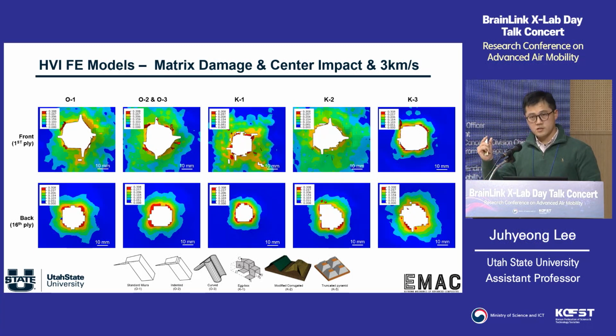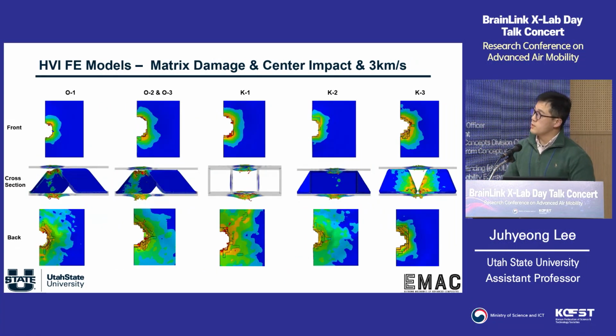So by simply changing the periodic patterns of the unit cell, you have a huge variation in the impact, right? So by studying the optimal shape design and also choosing a different material selection, you may block all the external impact compactly. Yeah. So this one is matrix damage volume-wise. You can see the impact side damage and then through-thickness damage as well as the back side. Again, you can see the huge variation in terms of the damage and failure of your fold core sandwich panel.